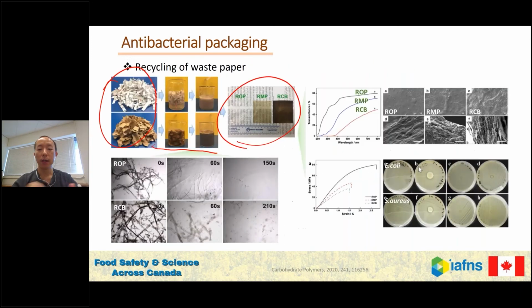For example, in this work, we just immerse our hydrogel film in the zinc oxide solution and the essential oil solution. And after that, we just dry the film to get the antibacterial material. And after that, we can see those materials, they have very good antibacterial capacity. And at the same time, they are made by cellulose. So those films are totally biodegradable.